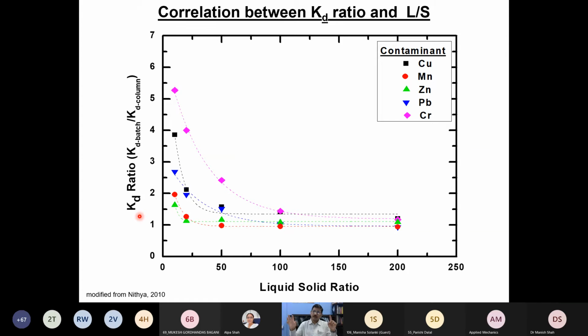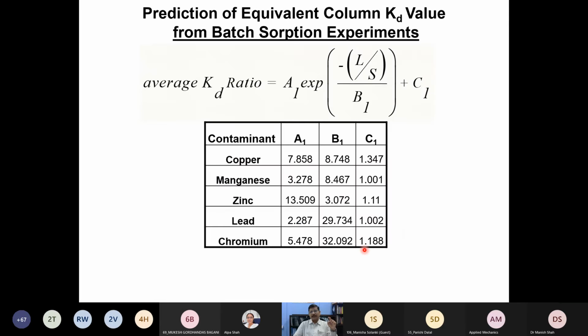And then the KD value we got from the centrifuge, we took it as the real value, and then we tried to normalize the batch versus this one, and we noticed how it changes with respect to the liquid solid ratio. By knowing this average KD ratio, and then by fitting an experimental curve, we got an empirical equation with constant parameters A1, B1, C1. And these A1, B2 are related to almost 5 varieties of soils representing a broad range, from quartz sand to bentonite, two extreme cases. And then we have taken 5 varieties of contaminants, and these values are matching well.